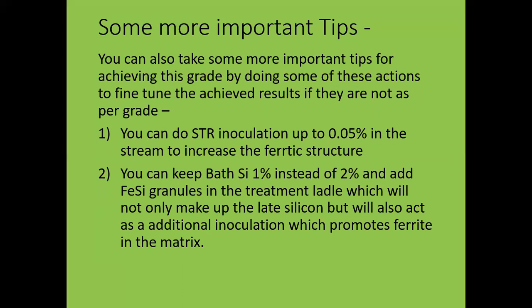stream inoculation up to 0.05% in the stream to increase the ferritic structure. So it is very important to add some stream inoculation up to 0.05% in the stream of the metal to increase the ferritic structure as a secondary inoculation, which helps you in reducing hardness, increasing the ferritic structure, and achieving